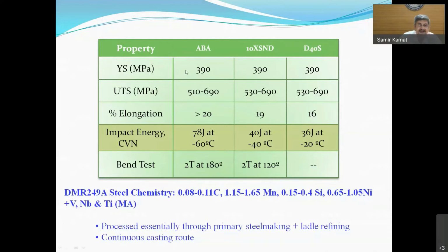So the composition of the steel is briefly given here. So it's a micro alloy, high strength, low alloy steel, that is ABA, which DMRL undertook the indigenization for. For people who are not metallurgists, it appears that once you know the composition, what is the big deal in making the steel? But let me tell you, knowing the composition is only knowing about 5% of what is required to make a steel. Because the real challenge is how to process the steel to get the desired microstructure, desired impurity contents in the steel to get the desired properties.